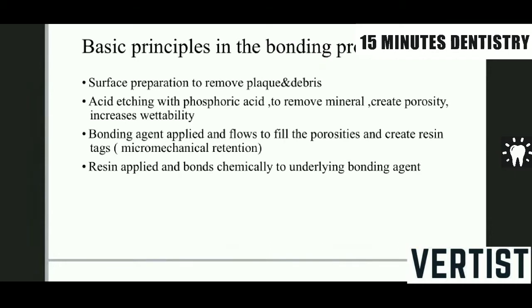In acid etching, whatever time you apply the acid, the same time should be used for rinsing the acid. That means you are supposed to wash that area and dry it. You are not supposed to desiccate the tooth before bonding. I mean to say that if you desiccate the tooth, then all the dentinal tubules will collapse, and then your bonding will be hampered. So there is a concept of wet bonding which is introduced nowadays.